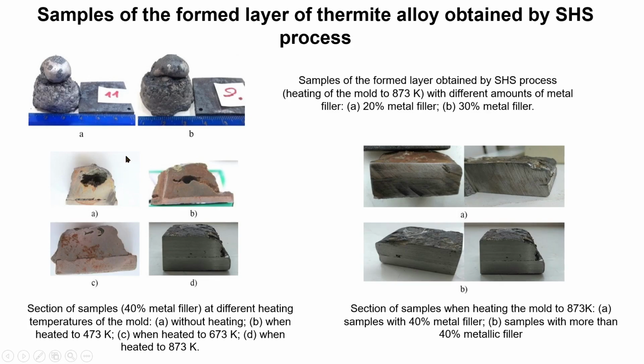Without heating, 473 kelvins, 673 kelvins, 873 kelvins, the best examples. When the thermite charge contains more than 40% of metal filler, regardless of the heating temperature of the mold, there is a decrease in melt temperature, which leads to significant porosity as well as the presence of oxidized areas in the joint, where it didn't melt. Like this and this.